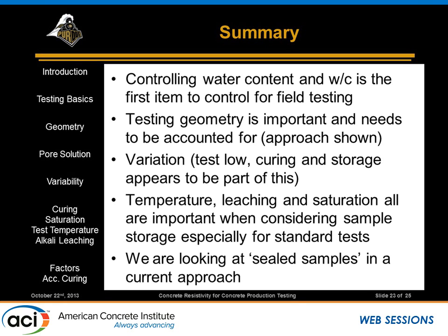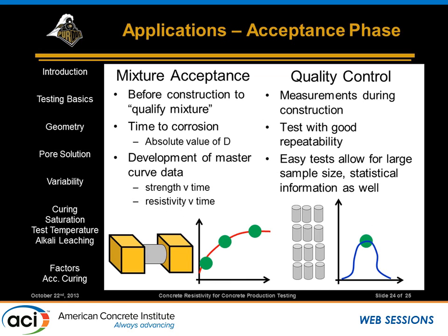We really need to tighten that up, and we really need to start to account for the leaching that can occur in those systems. Temperature, leaching, and saturation are all very important, and there are ways to describe this. We've begun an approach where we're really looking at sealed samples because we think from a production point of view this is something that could be easily done and easily implemented.